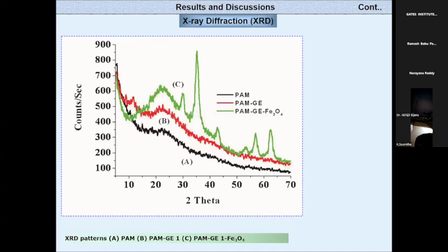This is the X-ray diffraction pattern of the polymers as well as the polymer nanocomposites. Why are we doing both FTIR and XRD techniques? We are converting iron ions into iron nanoparticles. If there is no conversion and only iron ions are present in the gel network, it will not be useful for application. So we are confirming whether there are really nanoparticles inside your gel or not. If you see some peaks, it is an indication of nanoparticles in your gel.